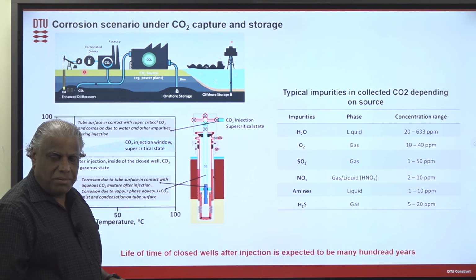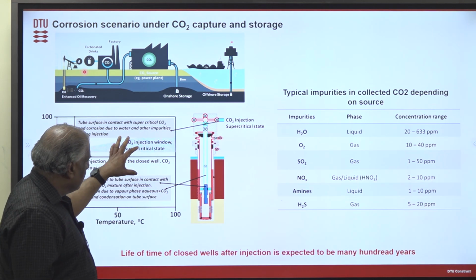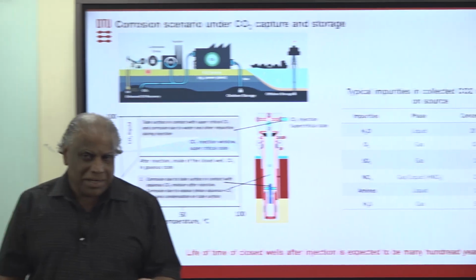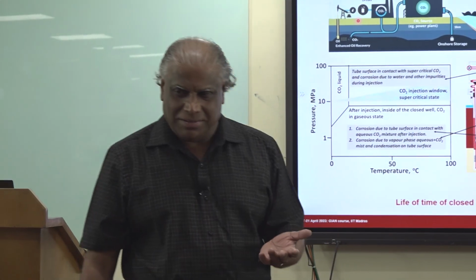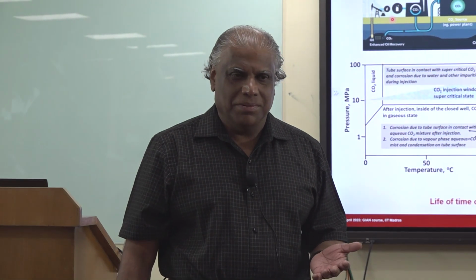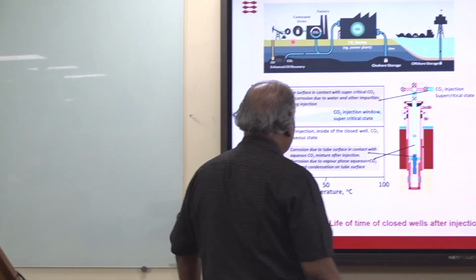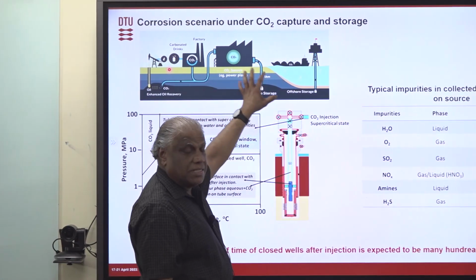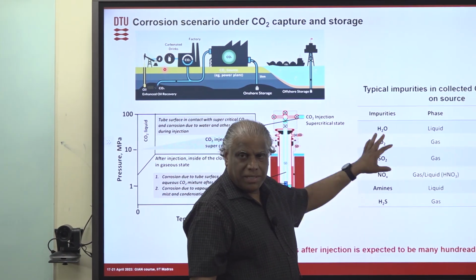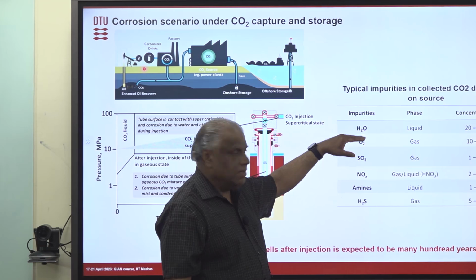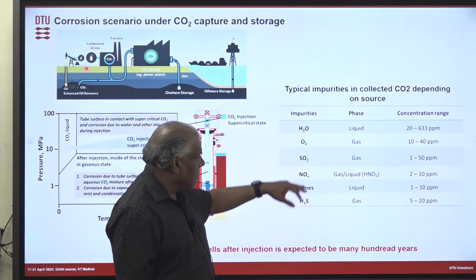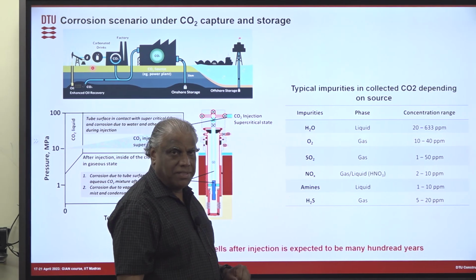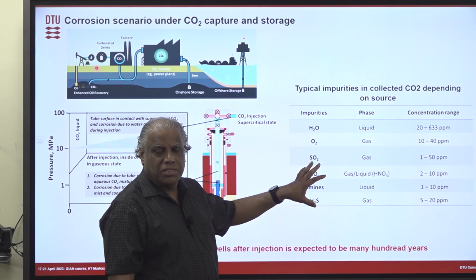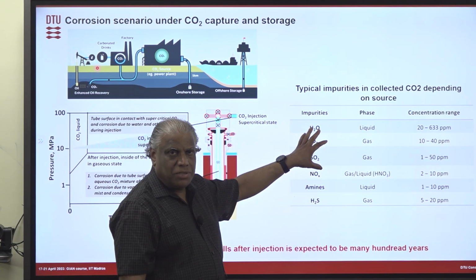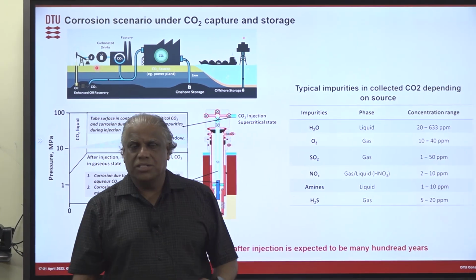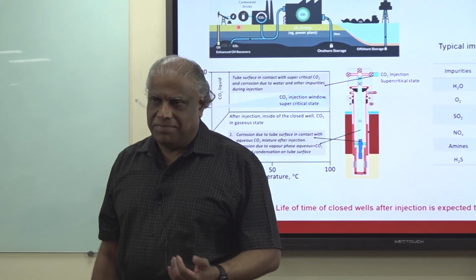Now coming to the corrosion problem. What is the corrosion problem? Supercritical CO2 itself is benign. It will not do anything. Liquid CO2 is not corrosive. The problem comes because any of the CO2 which is collected from the different sources can have some contamination. It can have a little bit of moisture content, and it can have oxygen content, it can have other types of things as a part of that. This is what is causing the problem. This water content, moisture content, and other gaseous content of tiny levels, that is what is causing the corrosive environment.